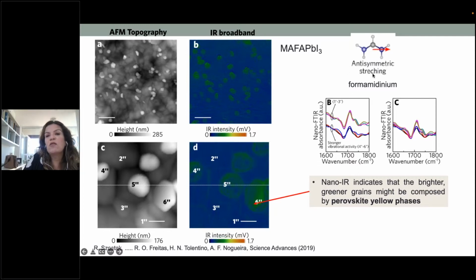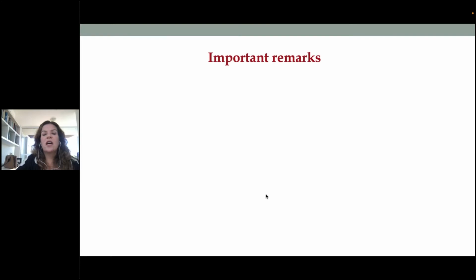grain. In this case, we are following the stretching of the formamidinium cation, and for the first time, we were able to see that these greener grains here are in fact the hexagonal phases. So these hexagonal phases are also well distributed in the film. So with that, I want to approach the end of my talk.